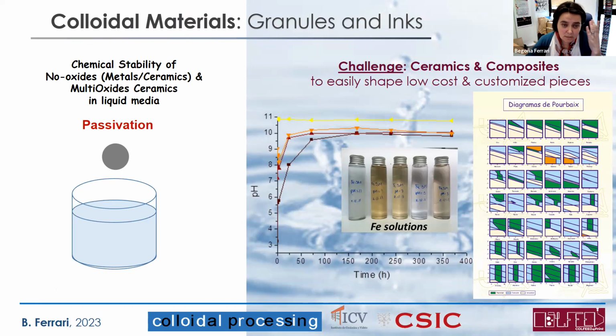So the first thing that we need to think about is the chemical stability of the particles. For example, when we are talking about non-oxide or metal, or even when we talk about trioxide or multi-oxide ceramics, we need to passivate the particles. We need to know how the particles behave in water, the chemistry. It's very important for metal, of course, and for non-oxide, but also in trioxide we need to avoid the leaching of cations, because if not, at the end of the process, we are going to lose the properties of our functional material.